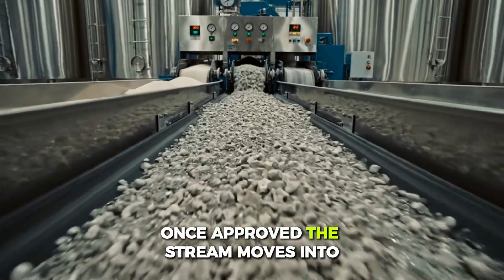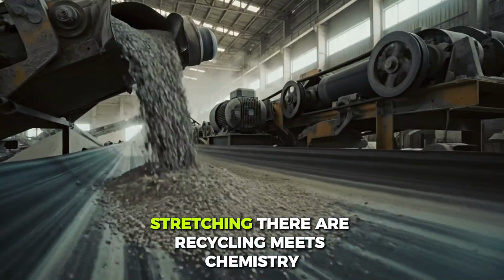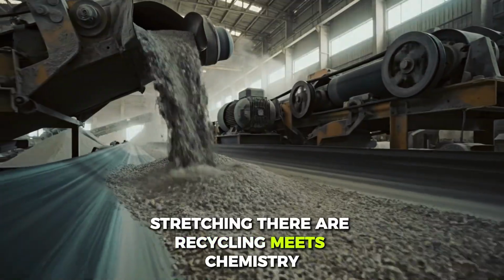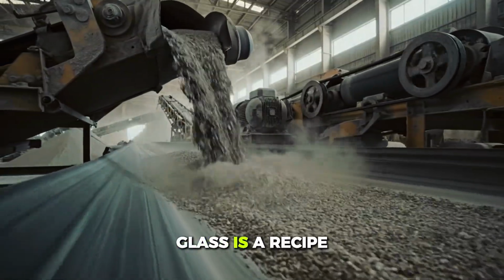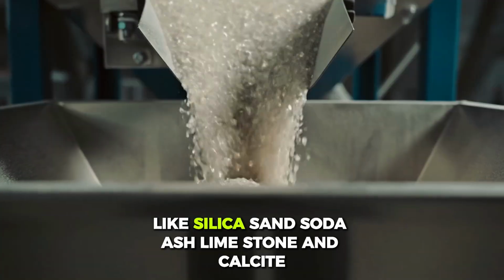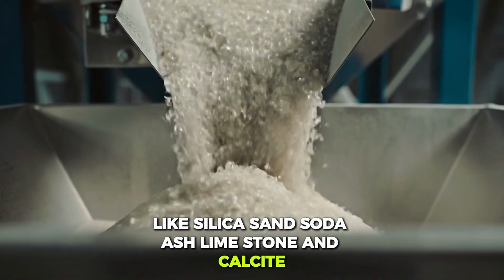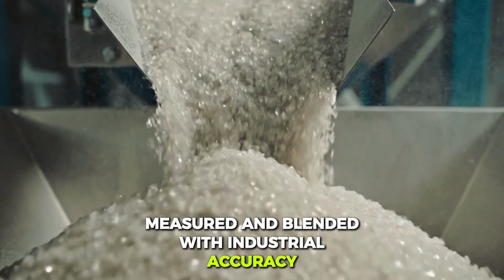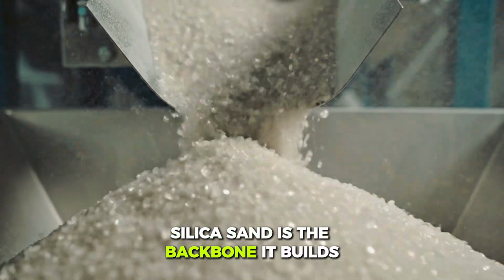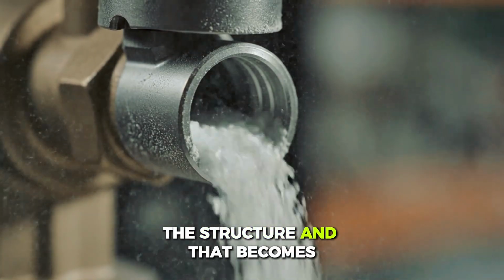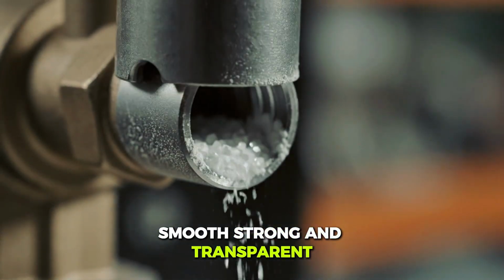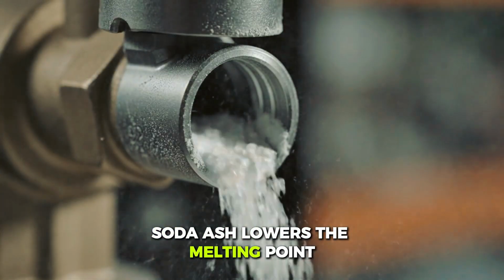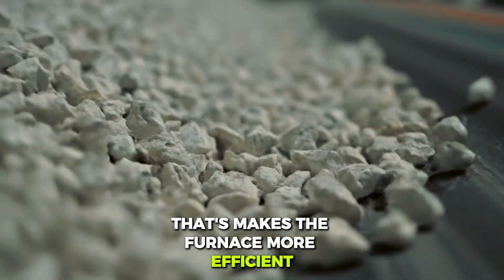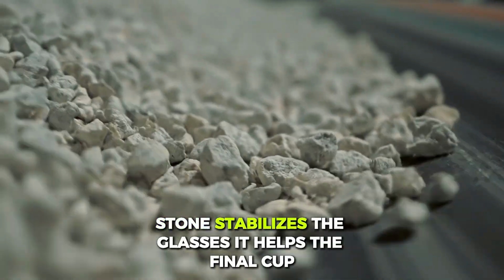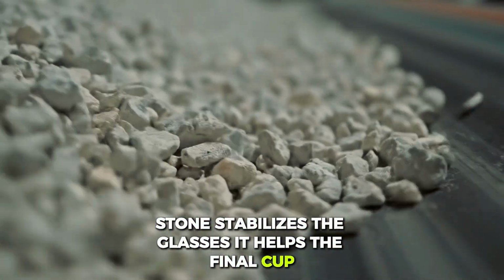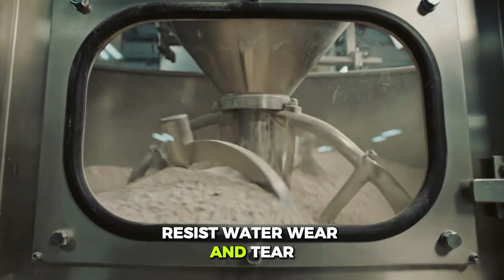Once approved, the stream moves into batching. There, recycling meets chemistry. Glass is a recipe: silica sand, soda ash, limestone and cullet, measured and blended with industrial accuracy. Silica sand is the backbone. It builds the structure that becomes smooth, strong and transparent. Soda ash lowers the melting point, which makes the furnace more efficient. Limestone stabilizes the glass. It helps the final cup resist water, wear and weathering.